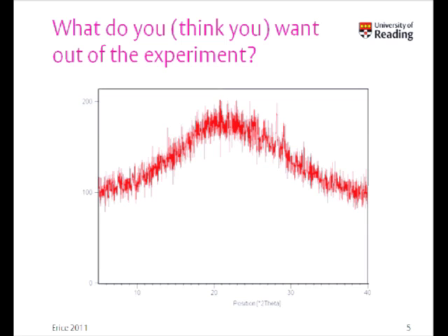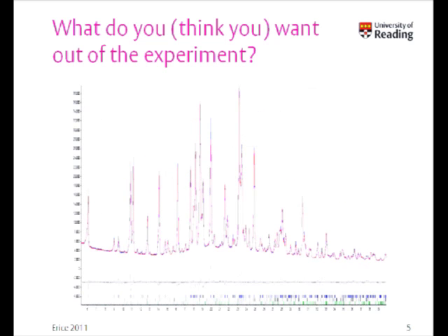And if he had anticipated the possibility of contaminant, shall we call them, starting material peaks, then he could have quite easily adjusted the experiment, counted for longer, and any residual crystalline material could have been picked up. So it's not so much what you want out of your experiments, what you think you want, or what you think you might want down the line.